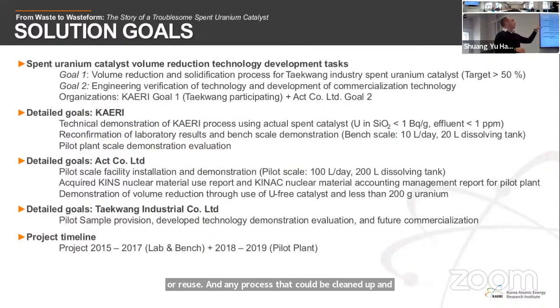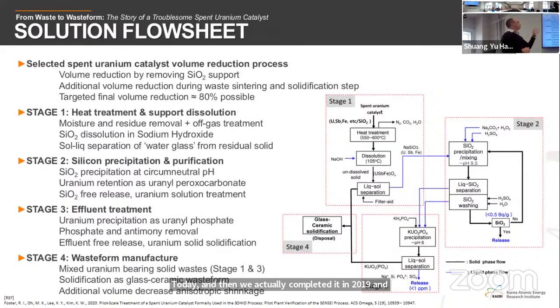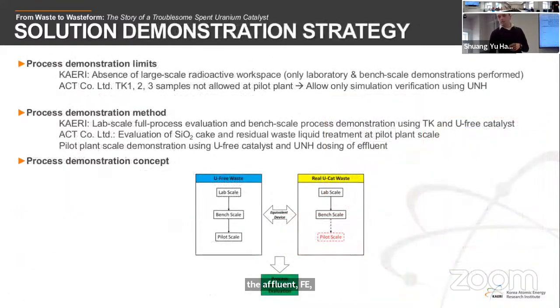The overall goal was that we would work at KAERI on development of the process on the bench scale and up to lab scale. And then, working with another company, we'd do pilot scale testing. The project timeline was 2015, so it started just before I arrived, for the lab and bench scale, and then we completed it in 2018 and 2019 with the pilot scale testing. Overall, the process we developed was split into 4 stages. We had a heat treatment and support dissolution stage, before a silicon precipitation purification stage, effluent treatment, and waste form manufacture. So essentially we could self-contain all of the waste, and we had ways to deal with the uranium-containing effluent and pipe it through to the final glass ceramic disposal stage.